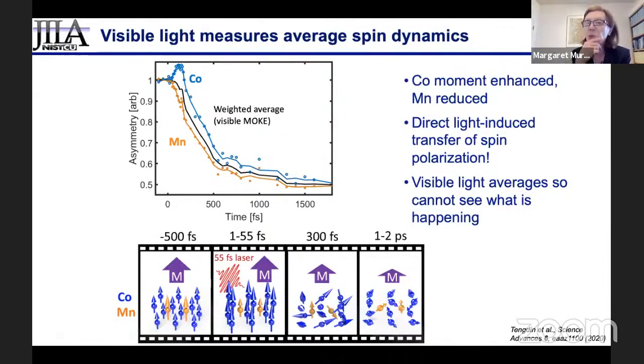And so you might ask, why were these excitations missed in the past? It's because when you look at these materials with visible light, one measures the average magnetism in the alloy or the multilayer, whereas with UV light, because of these different absorption edges, different colors of different harmonics lets us probe and look at what's happening in different sites, for example. So what's shown in black is what one would measure with visible light, which is just that standard demagnetization curve.